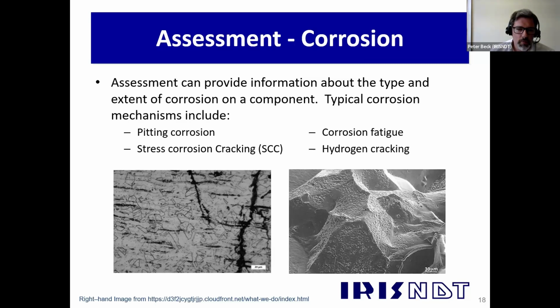We'd also look at stress corrosion cracking. So that's this image on the left at the bottom. So that's showing the transgranular cracking that you typically get with stress corrosion cracking in austenitic stainless steels. We can also look at corrosion fatigue, similar again. So you typically look at the crack tips and look for oxides and things like that that would show up as a sort of grey amorphous kind of region in the replicas.